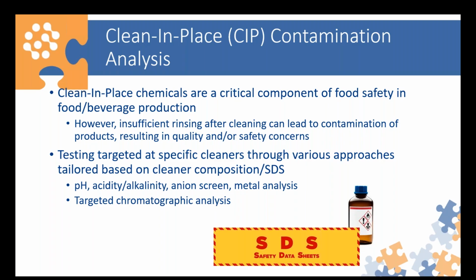In this case, we can compare a sample suspected to be contaminated versus a control sample known not to be contaminated, and evaluate them for things like pH, acidity, alkalinity, anion screening, for example the presence of phosphate anions, and metal analysis, and look to see if there are differences, elevated or lower levels of certain of these compounds in a potentially contaminated sample. Additionally, we can also do targeted chromatographic analysis, looking for cleaners that have surfactants or other ingredients that we can specifically target and look for lower levels of.